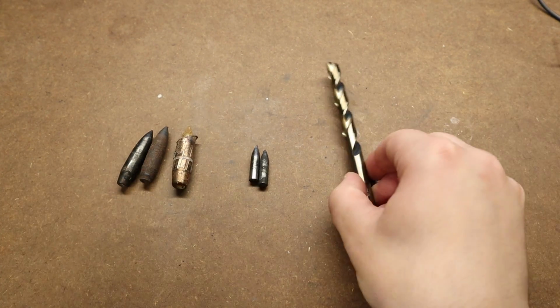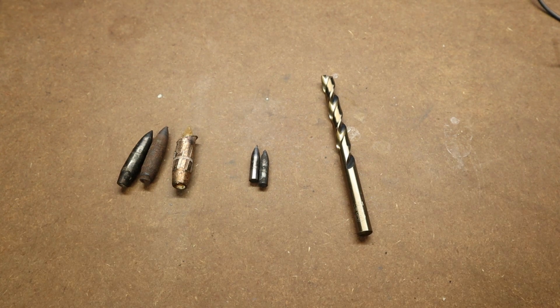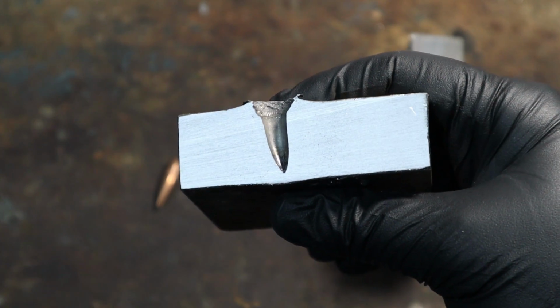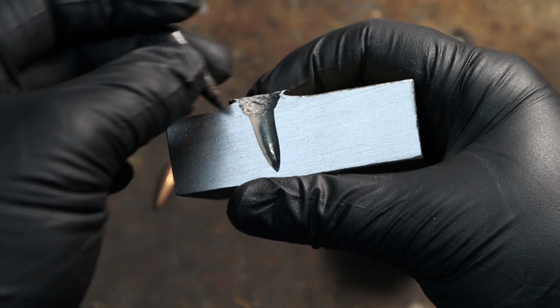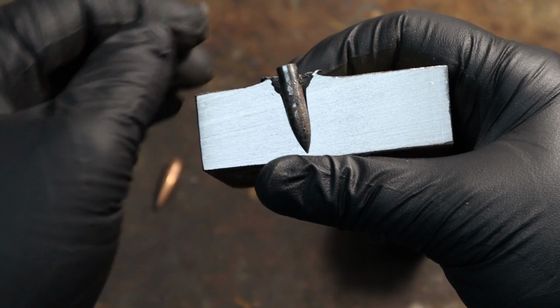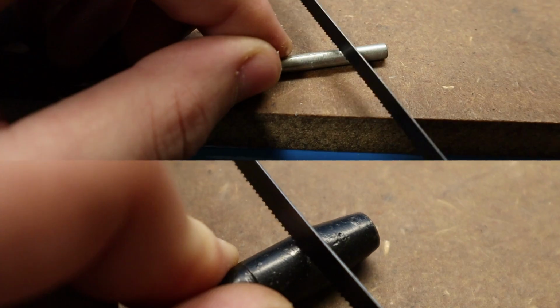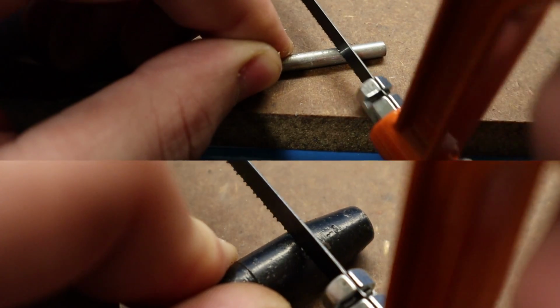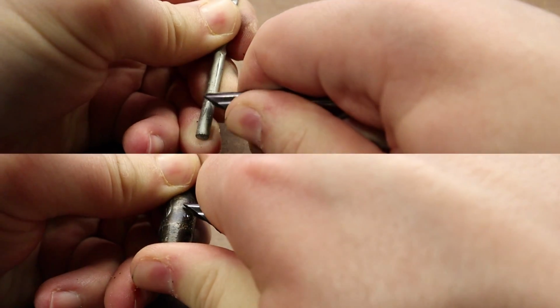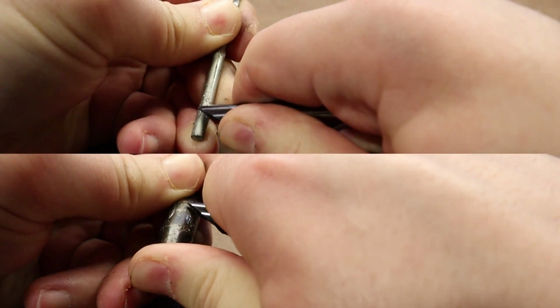If you think about it, what makes up a good penetrator also makes for a good drill bit. The exact composition and heat treat can be tweaked to tailor specific needs, but small penetrators for bullets are still made with some kind of tool steel. They allow reaching very high hardnesses due to the precipitation of metallic carbides without rendering the whole component too brittle, which is the reason why recovered penetrators tend to be either practically undeformed or shattered in 2 or more pieces. As you can see, both the AP core and the drill bit are untouched by steel tools but are easily scratched by a cemented carbide tip.